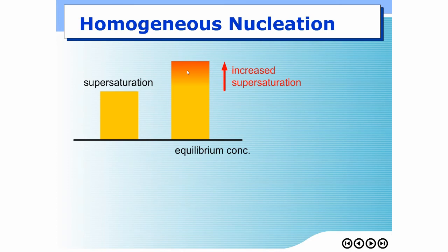So the higher the supersaturation level, the smaller the particles that you can get. How can we get this high supersaturation level? You increase the rate of reaction. Right? Or theoretically, you can also decrease equilibrium concentration, decrease solubility by decreasing the temperature. When you decrease the temperature, equilibrium concentration will be decreased. At the same concentration in the solution, you can also achieve the supersaturation level as well. Alright?